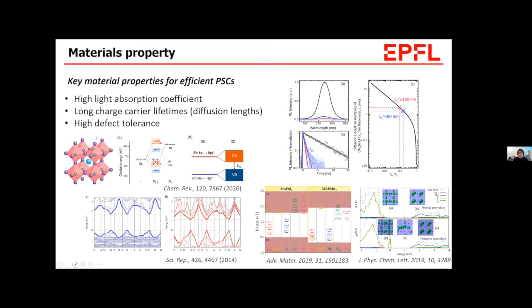And also, perovskites have long charge carrier lifetimes and long diffusion lengths. So the photogenerated charge carriers can migrate a long distance to be well collected at the electrodes without recombination. And lastly, perovskite is defect tolerant. For example, in traditional semiconductors, defect states significantly involve non-radiative recombination. But interestingly, even though perovskite also has defect states, the charge carrier lifetimes and diffusion lengths are exceptionally long in perovskite. So this indicates that the defect states in perovskite are electrically benign and defect tolerant.